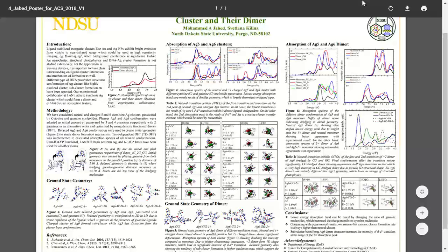We tried to figure out the conformations or mechanism of the dimer formation. Since we don't have any spectroscopic result, we started in the very beginning with a lot of different degrees of freedom to make conformations. In primary cases, we started with the lowest bare silver cluster conformations, and then we ligated with, say, cytosine mainly, and in another study we started with cytosine mixed with guanine.